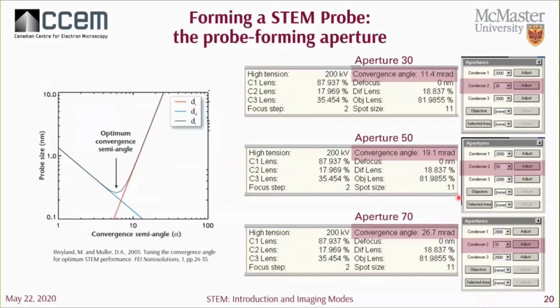So you want to choose a convergence angle that minimizes the contribution of spherical aberration. This is a graph showing you the contribution of spherical aberration in red and the diffraction limitation in blue. At small convergence angles, you have a diffraction limited probe. And then at a higher convergence angle, you have a finer probe, but you have increased contribution of spherical aberrations. So we want to choose a happy medium between these two, and then choose the right convergence angle for your particular system.